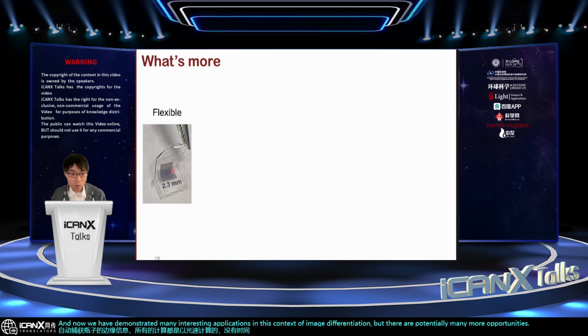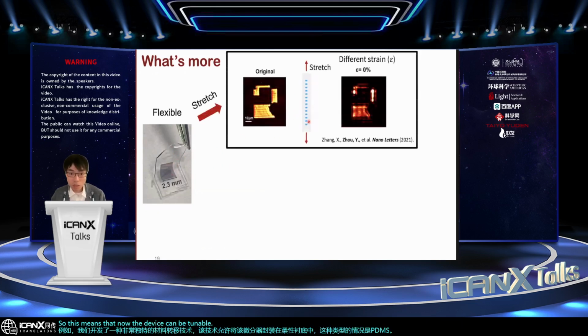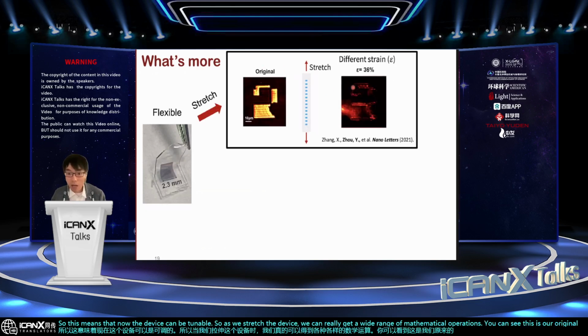For example, we developed a very unique material transfer technique which allows this differentiator to be encapsulated in a flexible substrate. In this case it is PDMS. So this means that now the device can be tunable. As we stretch the device, we can really get a wide range of mathematical operations. You can see this is our original image, and this video shows the processed image as we stretch the device. You can see now we can get a wide range of mathematical operations by stretching our device.